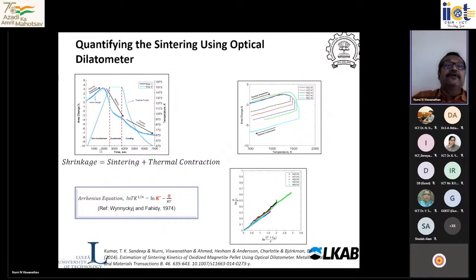For example, how the area changes as a function of time is shown here. Of course, there are two phenomena again here. One, as the temperature changes, there is an expansion. So the pellet expands, so the area increases. But you can see that because of sintering, the pellet also shrinks. So there are two phenomena, but expansion can be very easily taken care of. We know there is a thermal expansion coefficient, so it can be taken care of.